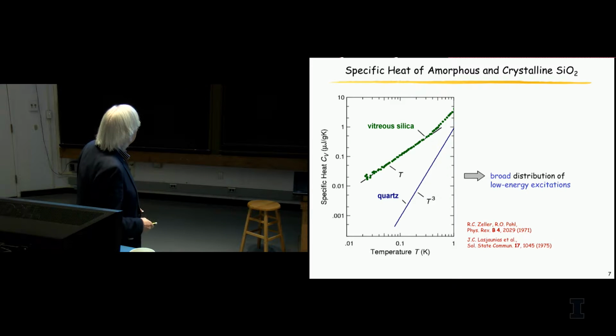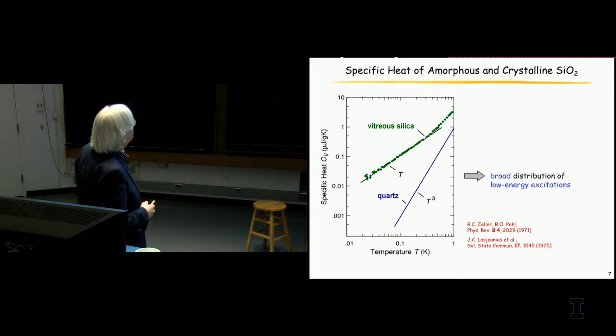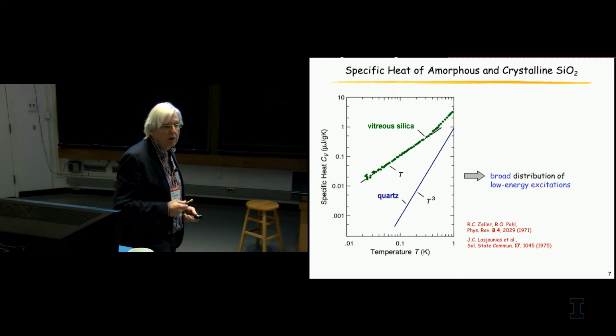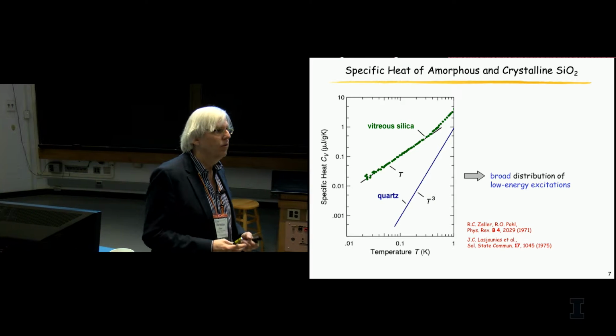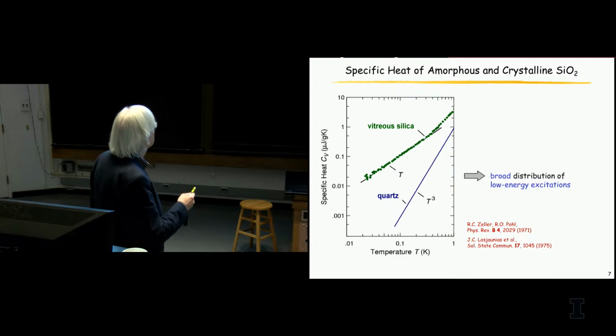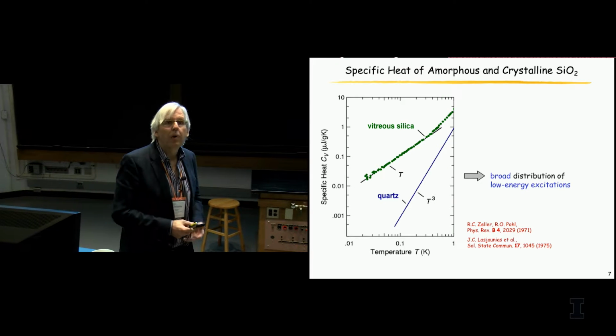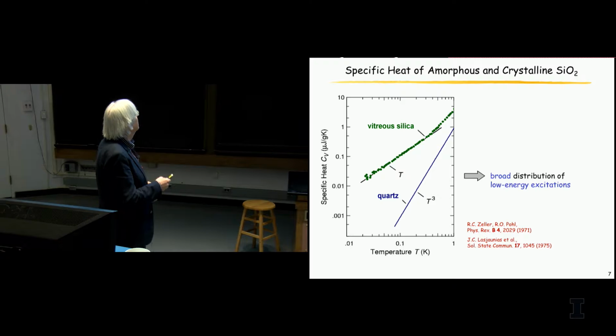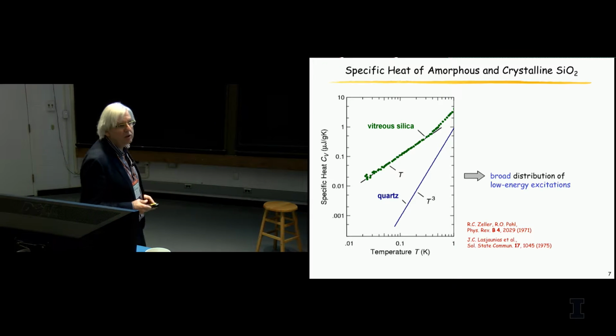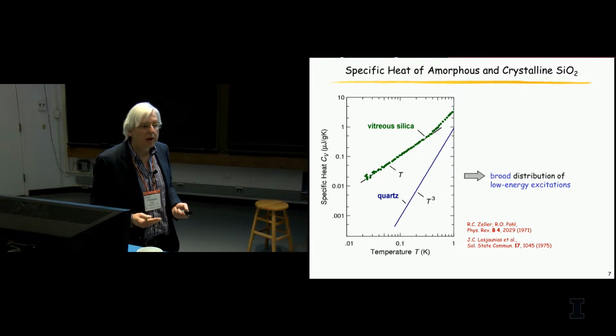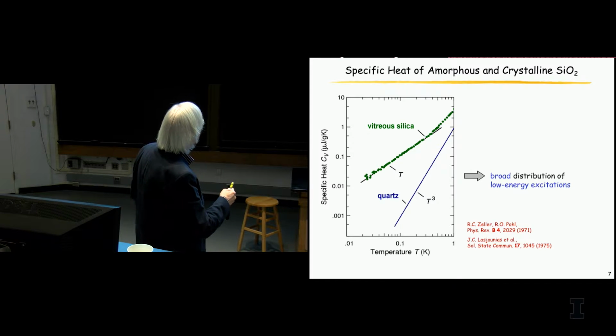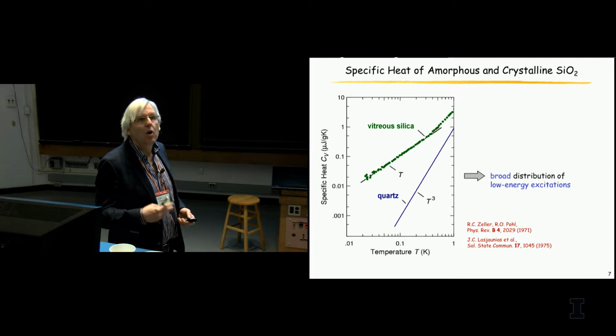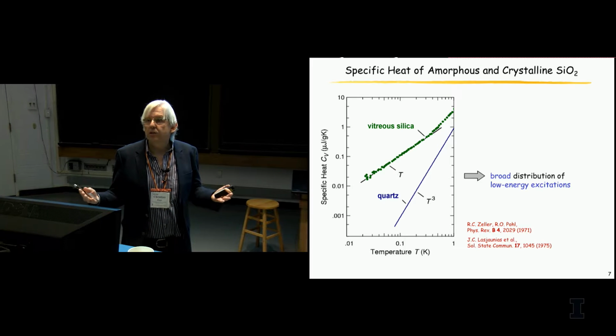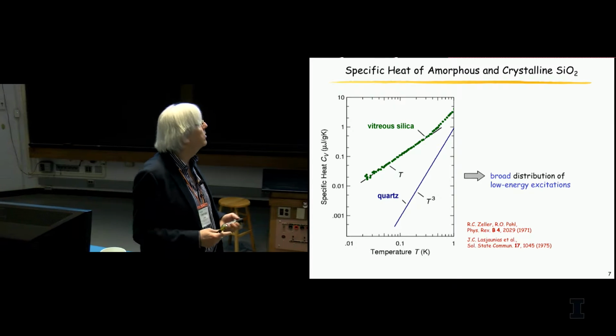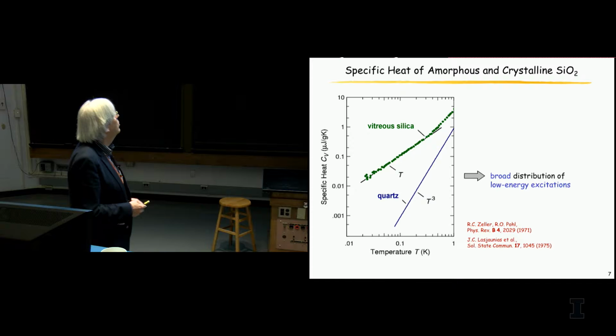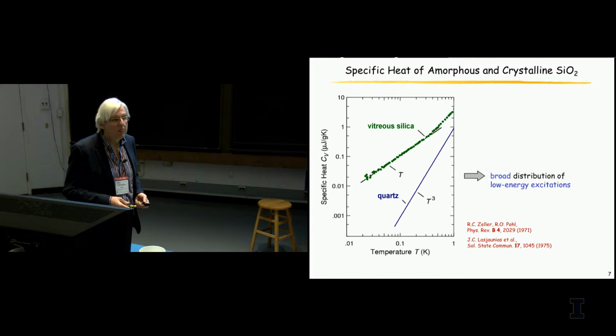Now, if you cool down a glass and measure the specific heat at the lowest temperatures, it deviates strongly from its crystalline counterpart. The crystal obeys the Debye law, but in the glass you find a large additional amount of excitations, and moreover, the specific heat varies linearly with temperature, which indicates that you have a constant density of states. So there are additional excitations beyond phonons, and they are broadly distributed.